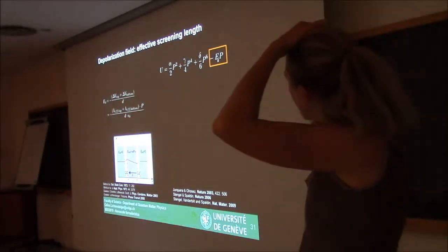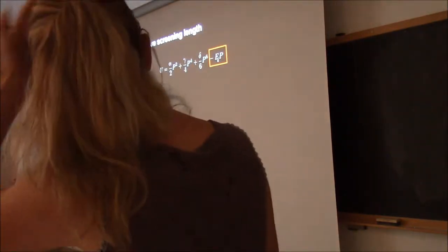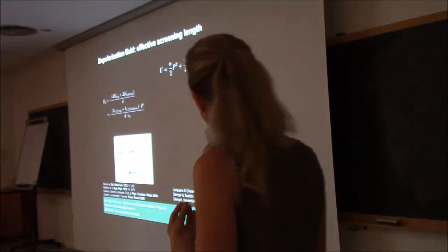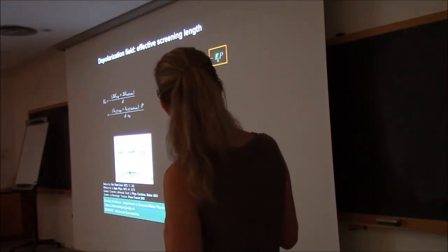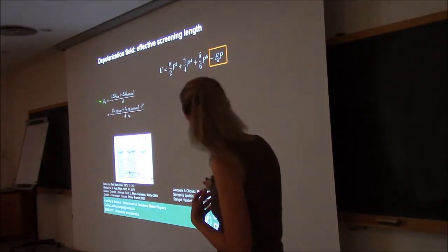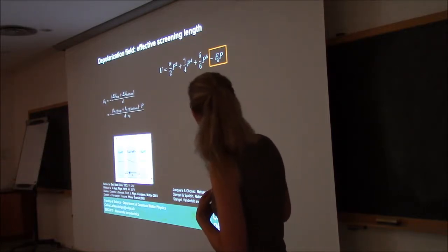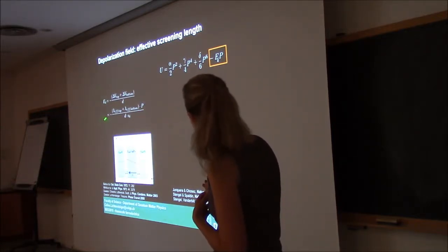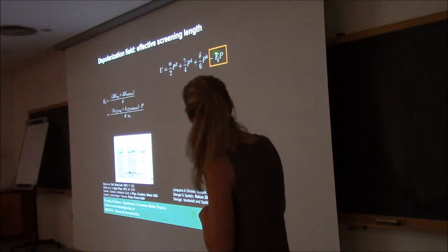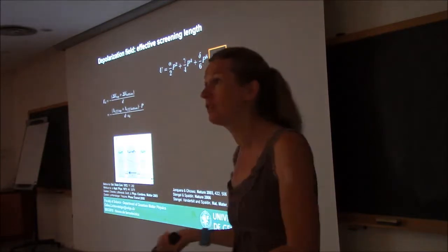Okay, so we started the lecture by looking at the model Hamiltonian and the Ginzburg-Landau approach. In terms of the energy of your material, when you have this depolarization field, you take again the expression of the energy of your material, and you add a term that goes as minus E_d dot P. So that means that because you have this non-zero depolarization field, you have an energy cost. So you see that the field here goes anti-parallel to the polarization, and so when you add this term, actually it costs some energy, so it's a positive term in energy.